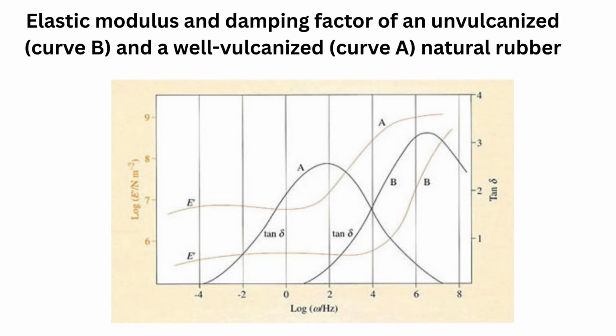Different rubbers will have different curves, and some care is needed in rubber product design to match the material with expected imposed frequencies. Fillers such as carbon black will also affect the shape and position of the damping maximum. At very high frequencies, omega equals 10 to the power of 8 cycles per second, or hertz, rubber is very stiff with a glass-like modulus. At these frequencies, the polymer molecules do not have time to react in response to the forcing oscillations.